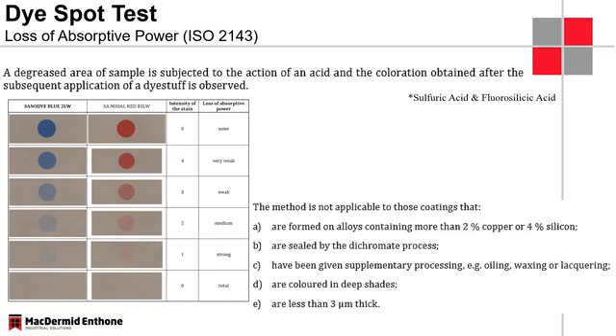And what we do then is we rinse off this acidic solution and we apply a drop of dye onto the surface. So for surfaces that have been opened up by this acid, they will absorb a significant amount of dye, which will then be reflected in a color change of the surface. So what we see here in this table is from the top where parts have absorbed a lot of dye, and this would be a very, very poorly sealed surface, and it would be a no pass. If we work down this table here, we'll see the bottom two pictures where you can hardly see any change or coloration of the anodized surface, and this is really what we're aiming for, and what would determine that we have done a good job sealing the components.